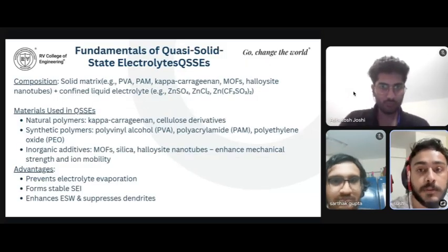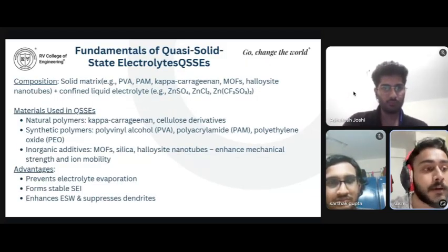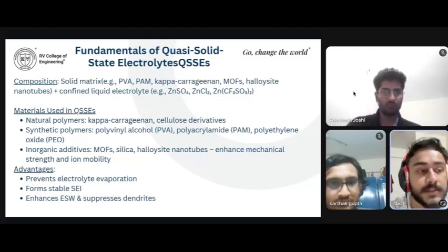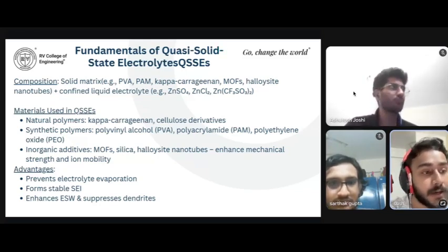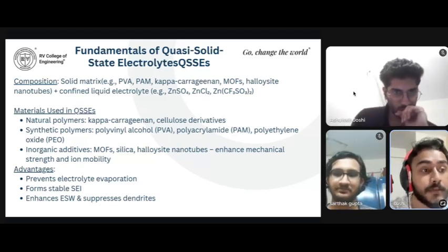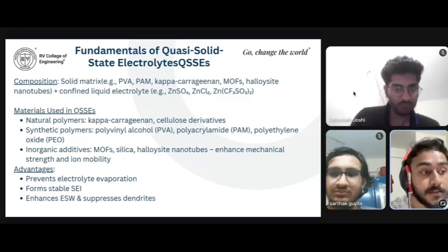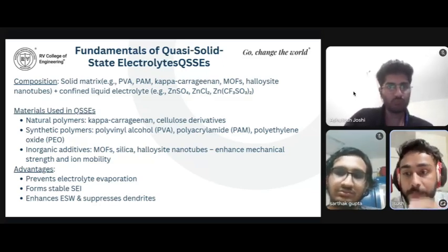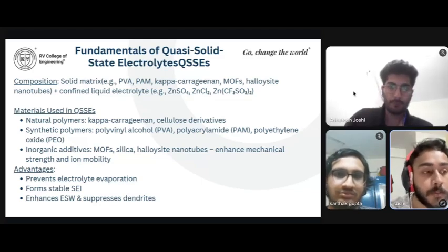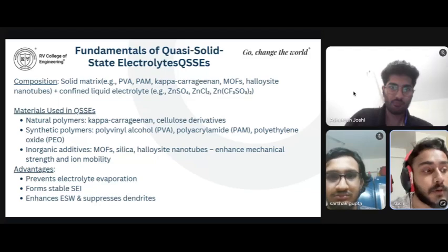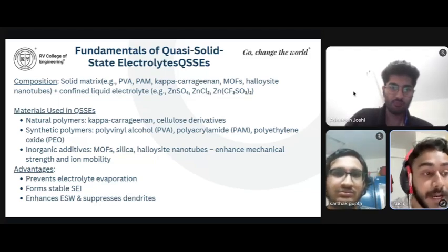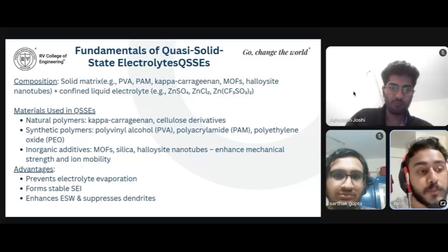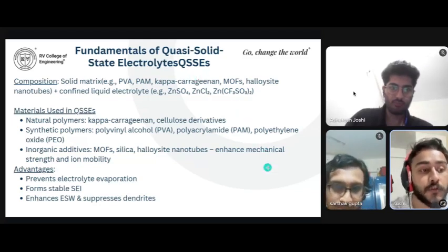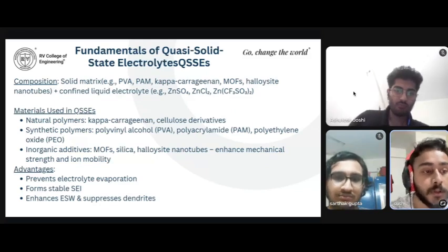So now we will talk about the fundamentals of quasi-solid-state electrolytes, their composition and materials. QSSEs are made up of two main components. The first one is the solid matrix such as PVA, polyvinyl alcohol, kappa carrageenan or MOFs. The second one is a confined liquid electrolyte such as zinc sulfate or zinc chloride. The materials can be categorized as natural polymers like cellulose or kappa carrageenan, synthetic polymers like polyvinyl alcohol and polyethylene oxide, and inorganic additives like MOFs and silica, which help improve both the strength and ionic mobility. These combinations help prevent electrolyte evaporation, form stable SEI layers, and suppress dendrite growth. Now next slide.